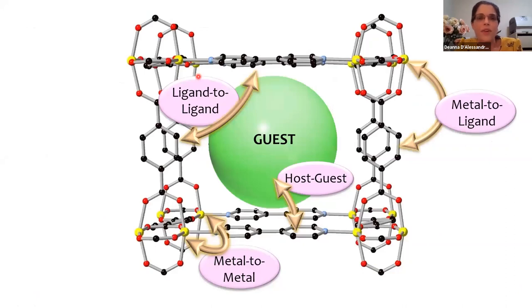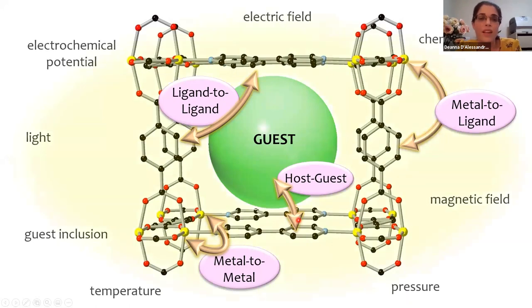So just thinking really first about one pore of a generic metal organic framework, and the exact framework doesn't matter so much here, but we can envisage, of course, a range of different types of charge transfer interactions, for example, metal to metal, ligand to ligand, or metal to ligand interactions. Of course, the beauty of the metal organic framework is the presence of these pores. And so we can also envisage host-guest interactions as well. These interactions might be intrinsic to the framework backbone itself, but of course, if we apply some type of external stimuli like electrochemical potential or even chemical potential, electric field, magnetic field, or even just including some type of guest, then of course we can alter the properties of the framework itself.